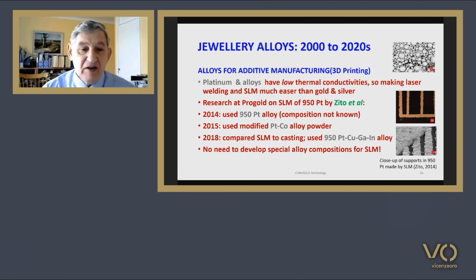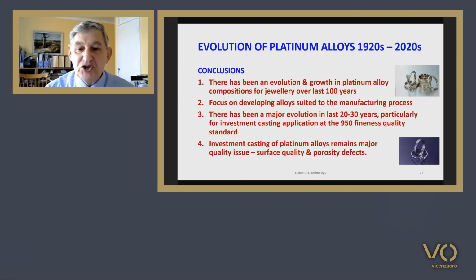That is the end of my review of platinum alloys. So let's make a few conclusions. There's been an evolution and growth in platinum alloy compositions for jewellery over the last 100 years. The focus has been on developing alloys suited to the manufacturing process. There has been a major evolution in the last 20 to 30 years, particularly for investment casting application at the 950 fineness quality standard.